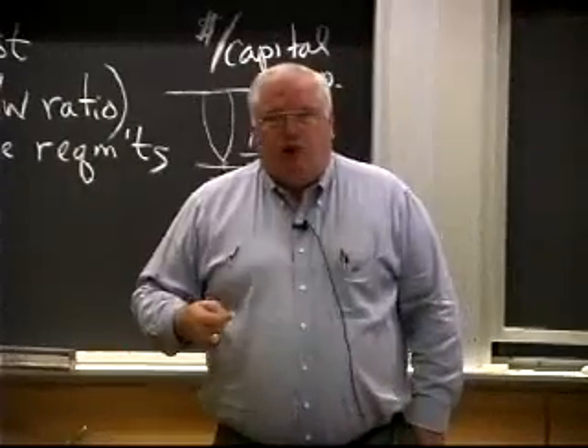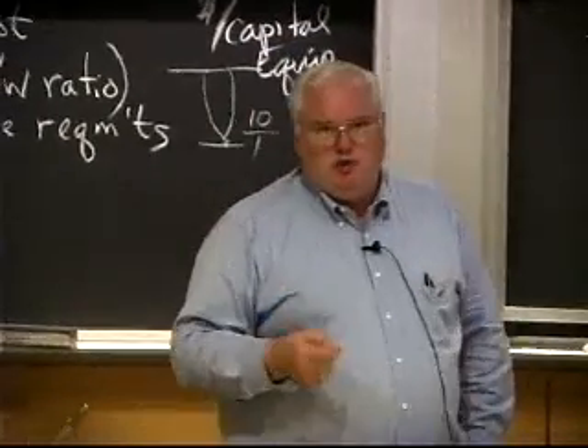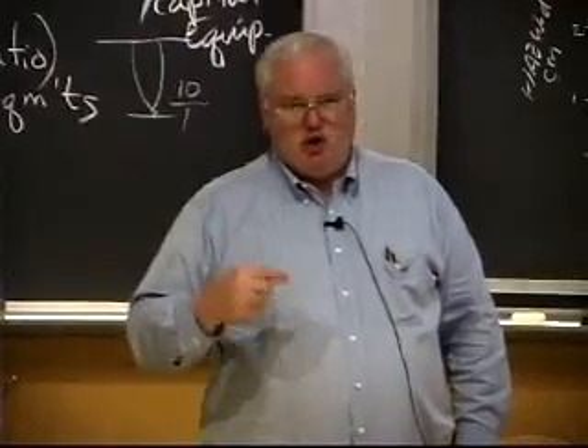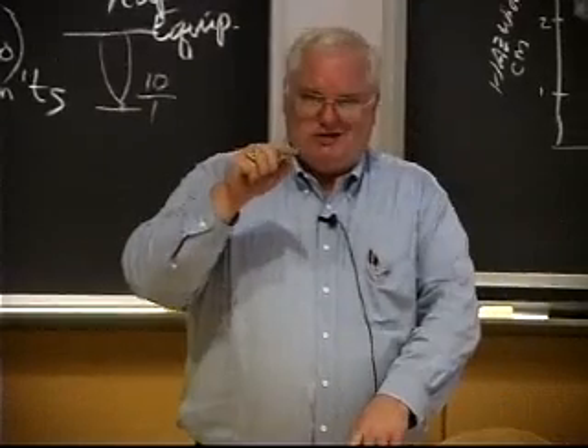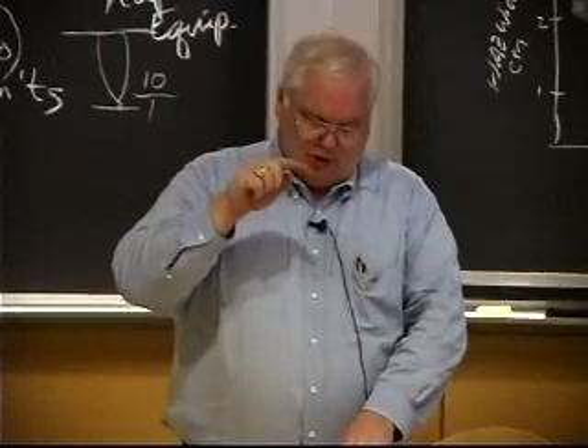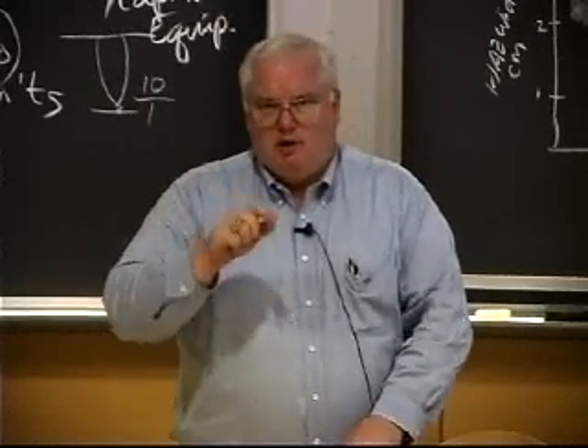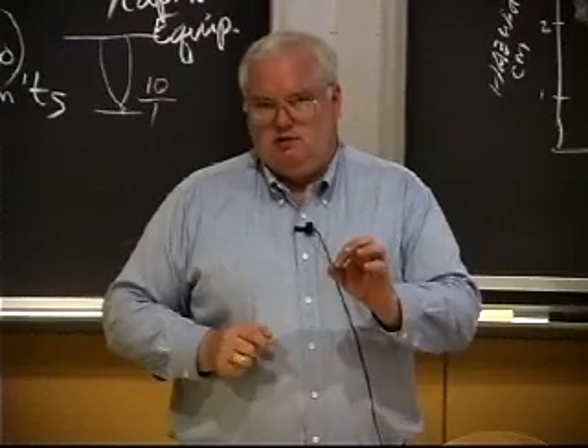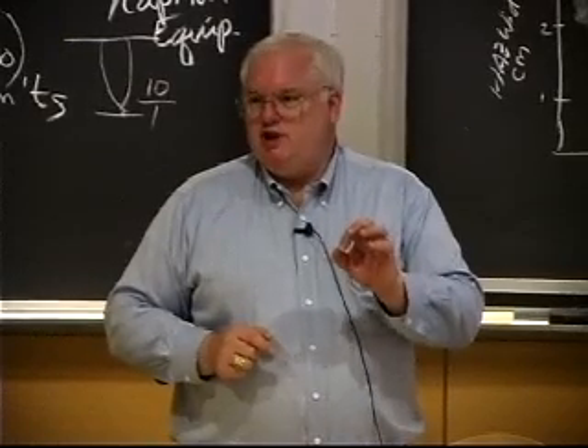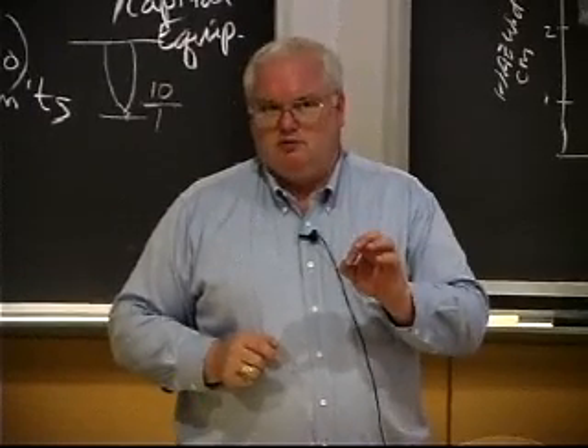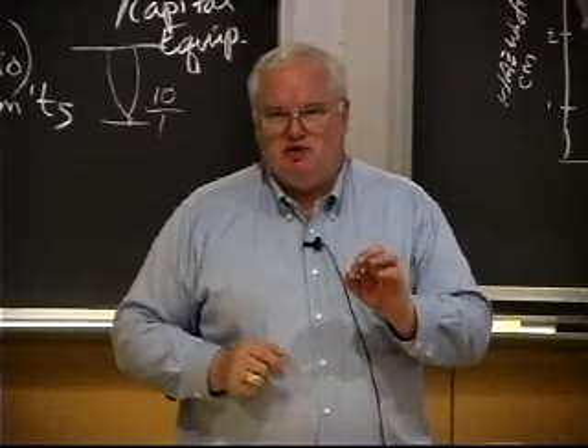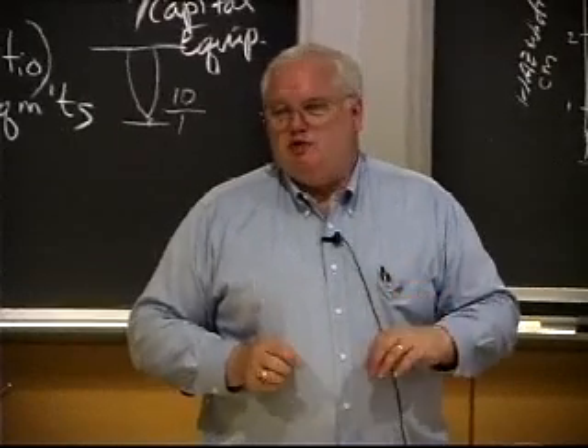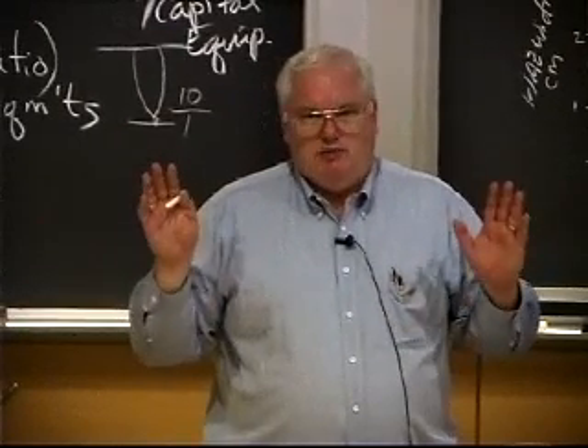They have made welds at the Welding Institute in Britain that have an aspect ratio of 200 to 1. A 20-inch thick sheet of aluminum, or block of aluminum, welded with only a 1/10 of an inch wide weld zone, 200 to 1 aspect ratio of that weld. That was just done to say it could be done.